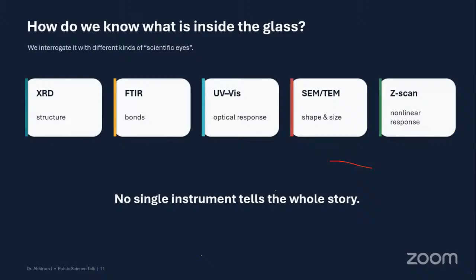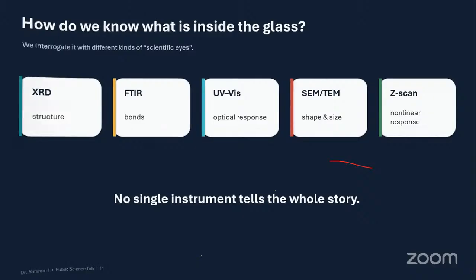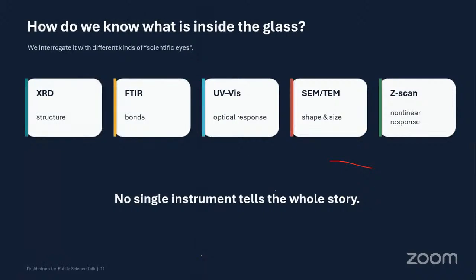And how do you get to know about it? One is by XRD, where you make the structural characterization. But again, since it's an amorphous network, since there is no long range order in it, there is no point in getting any crystalline signals from it. Then FTIR speaks about how the bond is being found between the BO4 region or BO3 region or Si. It just gives you the molecular bond structure. It doesn't clearly tell you how exactly is the structure of the glass that is present inside. So you are not able to get complete information from one single characterization. So you need to club all these characterizations and then you have to interpret what exactly happens.